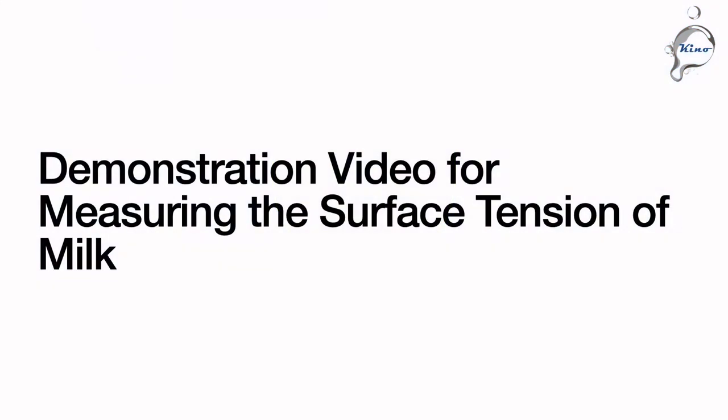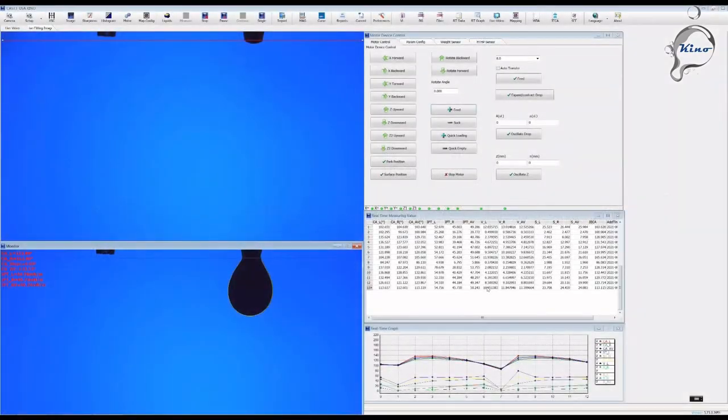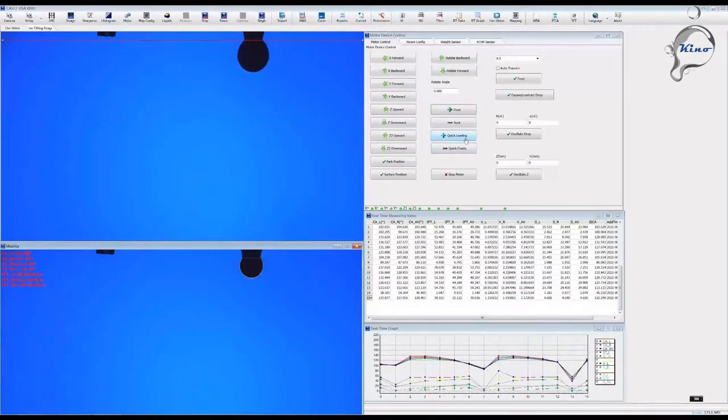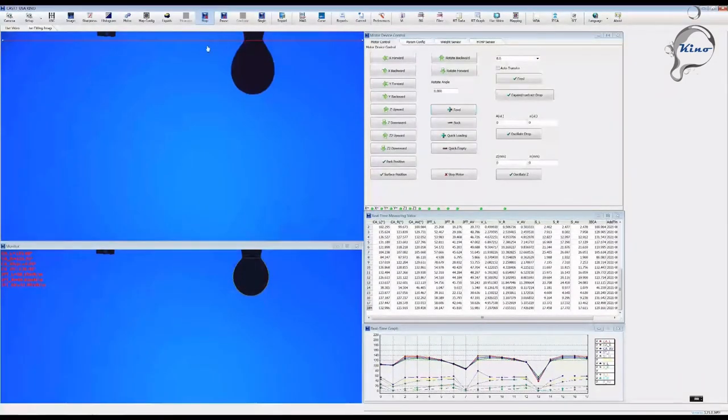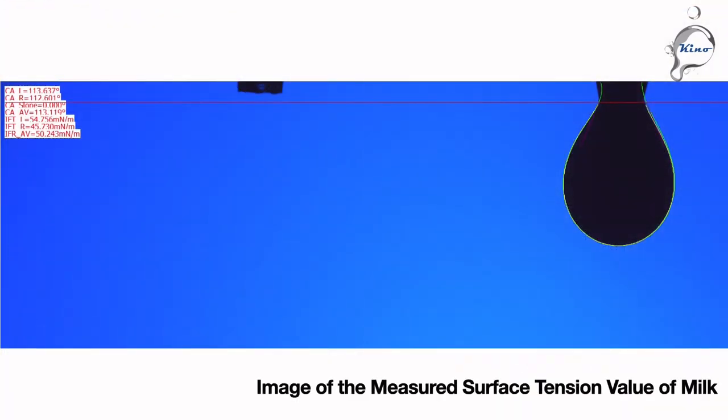The demonstration video for measuring the surface tension of milk. This is an image of the measured surface tension value of milk. The result of the measured surface tension value of milk is 50.243 millinewtons per meter. The surface tension value of milk is lower than that of water, indicating that if you